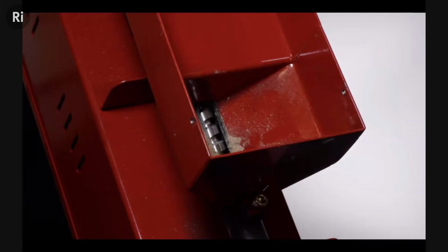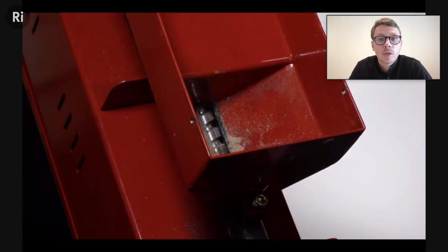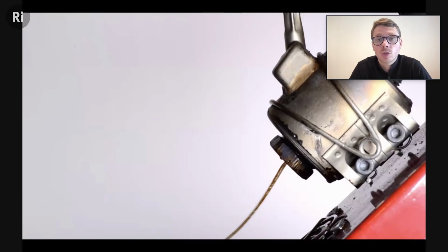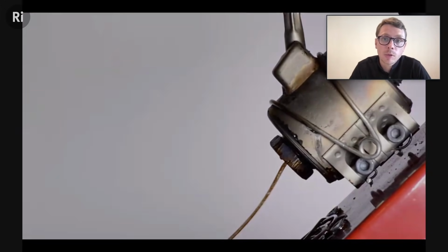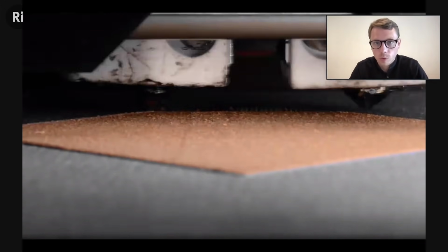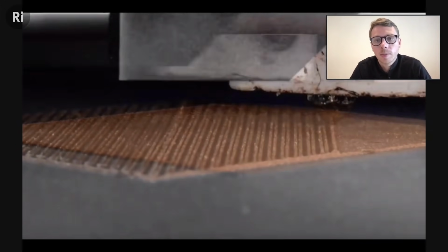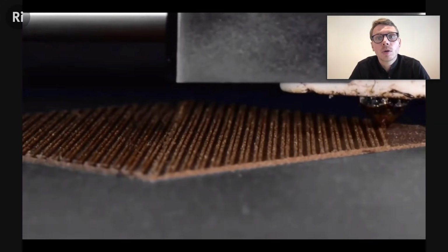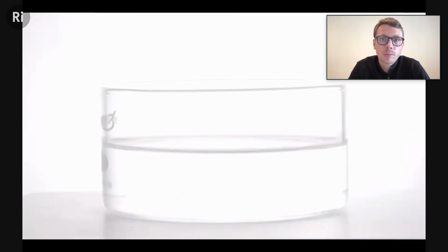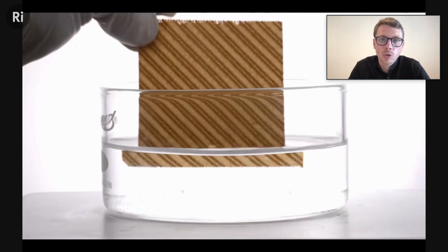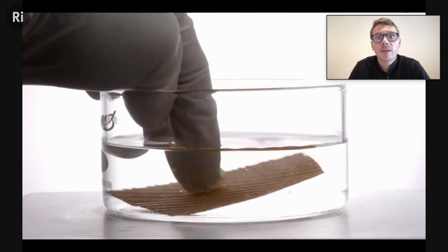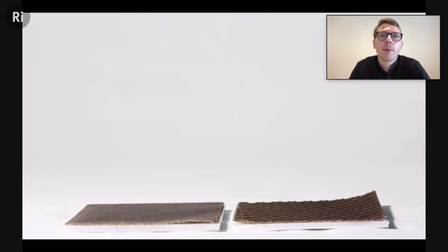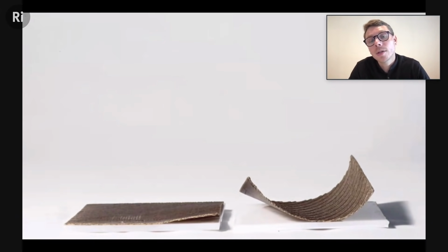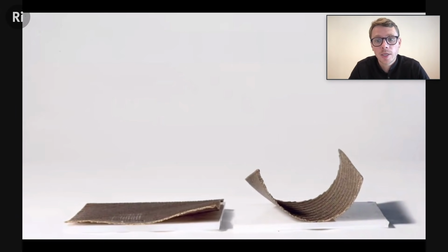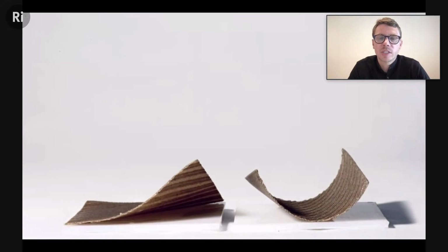So what we started to do was to create our own wood. We started to mix the wood and polymers together and extrude that. And in the beginning, we were making our own. And then you can now order wood filament as a material to print with. And we print our own wood grain. So we take the natural property of the wood to absorb and swell with moisture, but we have design freedom to design our own patterns. So depending on the printed pattern of the wood grain, you can get wood that behaves in different ways.